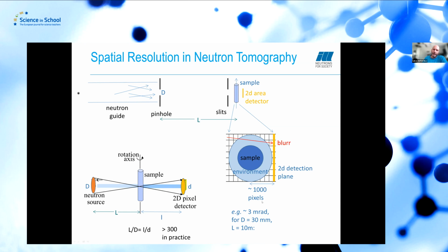And so what we see here, we get already with the 300, we get something like 3 milliradians. That means that in practice it doesn't hurt too much if we get blur circles in the order of 2 to 3 pixels.